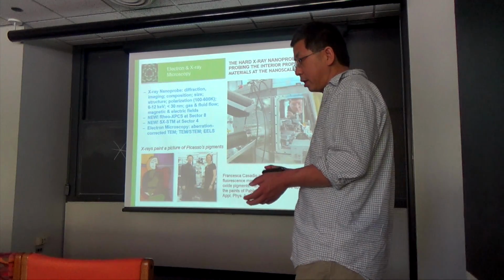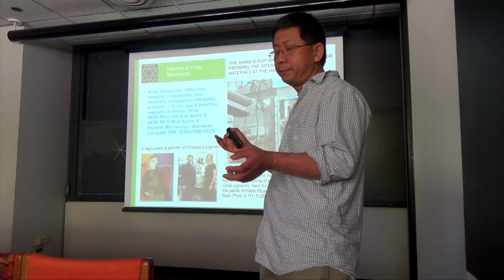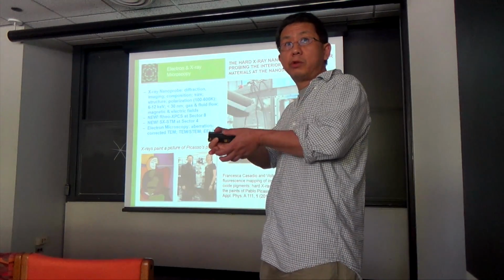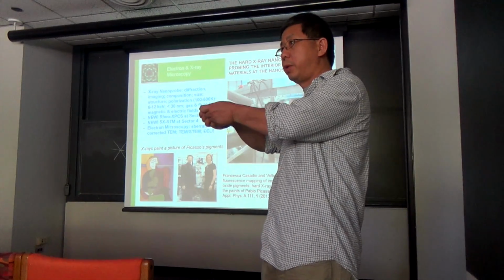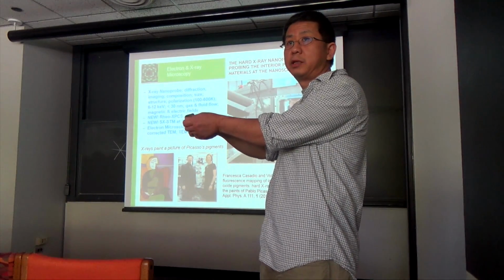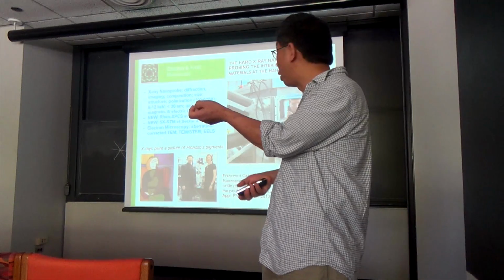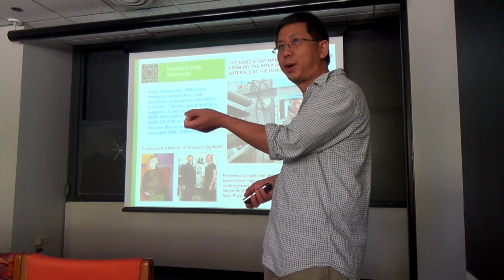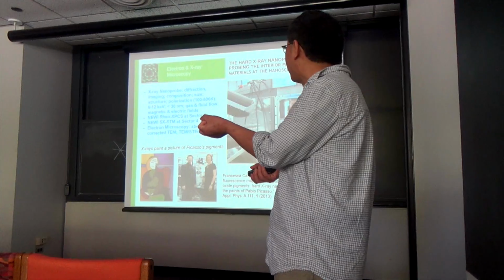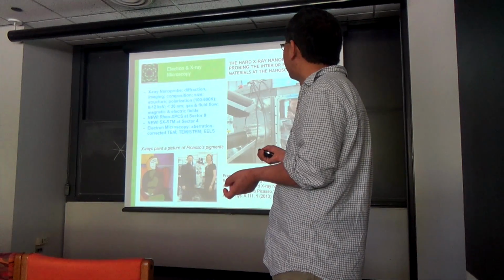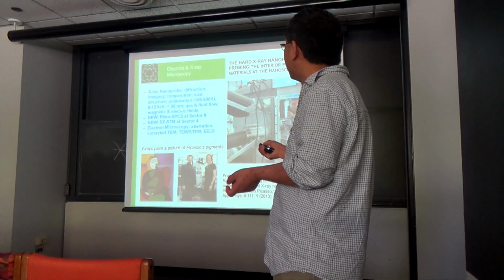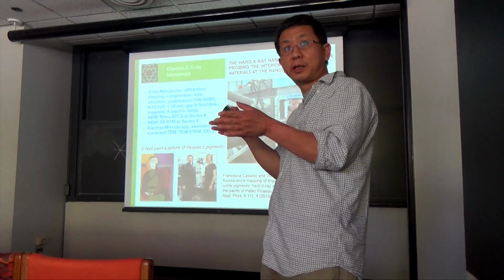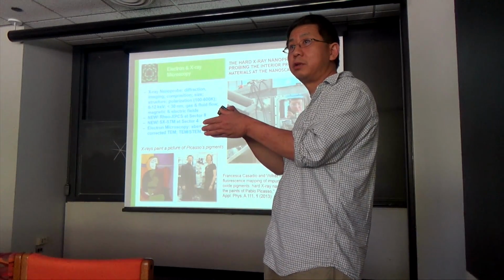So what it does is that it takes X-ray and it goes through an X-ray Fresnel zone plate and focuses the X-ray down to a very tiny spot. They're working very hard to make the spot as small as possible. The current reasonable spot size is about 30 nanometers. In some cases, depending on the technique, they can get down to 10 to 15 nanometers.